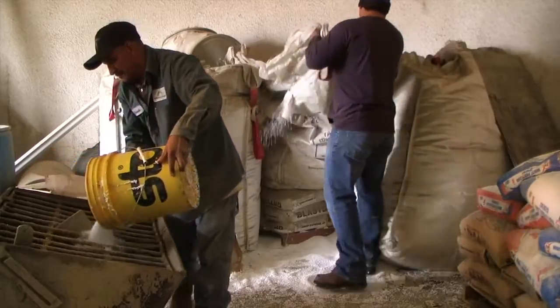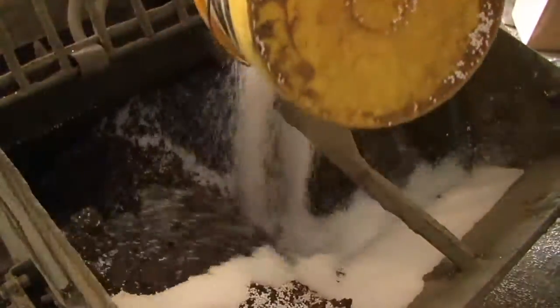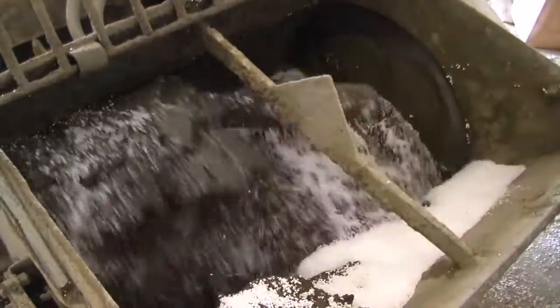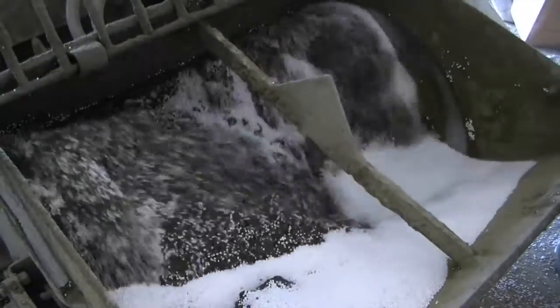You can see here us adding the Styrofoam beads to the concrete mix. We're adding six five-gallon buckets of Styrofoam beads, the equivalent of four five-gallon buckets of sand, two bags of cement, and the normal amount of water which is about eight to ten gallons.